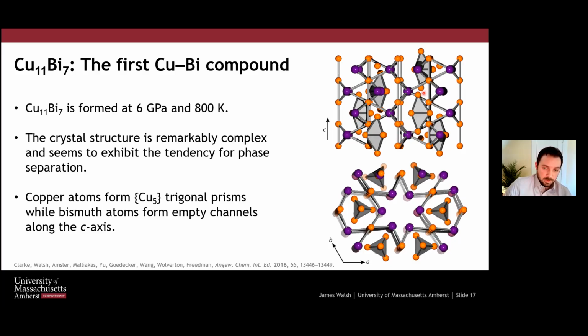And inside the phase, if we look, we can see hints of phase separation. So even though we've made this compound, there are still signs that the copper and the bismuth don't really want to be intimately bonded. And we can see that from these copper-5 trigonal prismatic moieties. So the copper is bonding to itself. And then we have these bismuth channels that run along the c-axis, where the bismuth is kind of staying with the other bismuth atoms. And so this is interesting to note that we can get this kind of complexity in a simple binary system. You know, the unit cell is relatively large for this system.